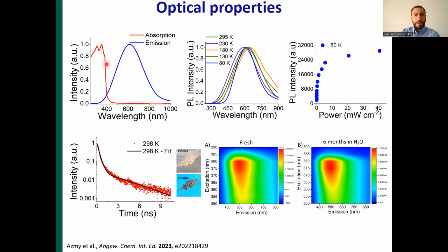As I mentioned earlier, the material is a direct bandgap semiconductor. However, in addition to porosity, the material is also a broad light emitter at room temperature. There is a large energy shift between the absorption and the emission spectra. We performed variable temperature PL studies, where we observed minuscule differences between both the PL peak position and the full width at half maximum of the peak. Time-resolved PL studies revealed a lifetime of around 3 nanoseconds, which correlates well to other broad lead bromide light emitters.